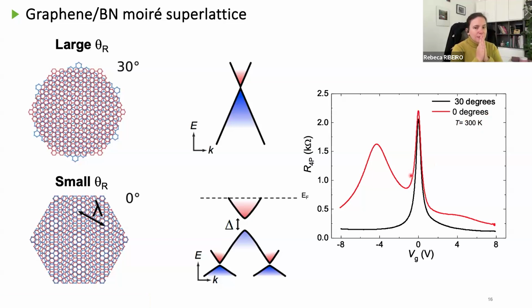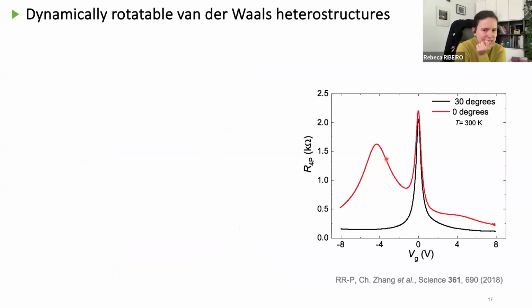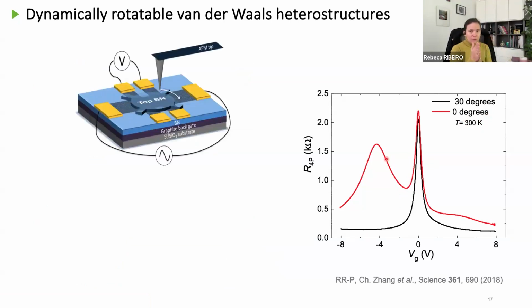Now, what we decided to do at the time is we wanted to go from one alignment to the other alignment in steps. Because what I didn't say before is that the way to do this is you stack the materials and they are fixed. You cannot change the angle anymore once you measure the transport. So in 2018, we developed a technique that, using an atomic force microscope tip, allows us to change the crystallographic alignment between these layers.